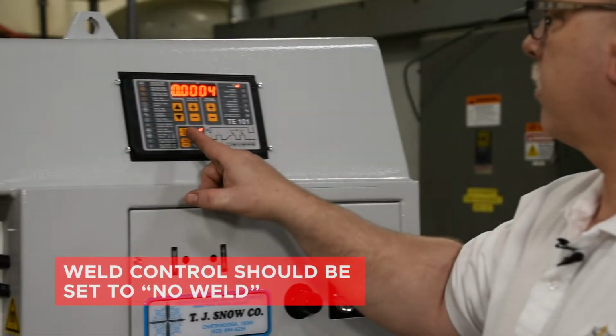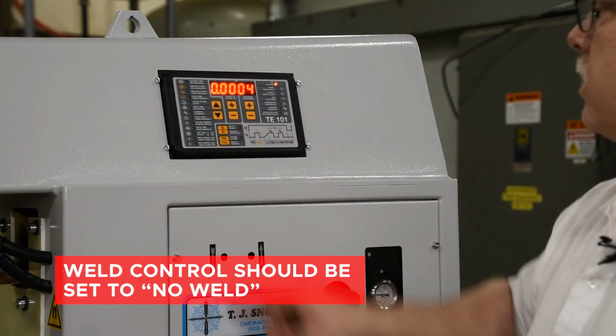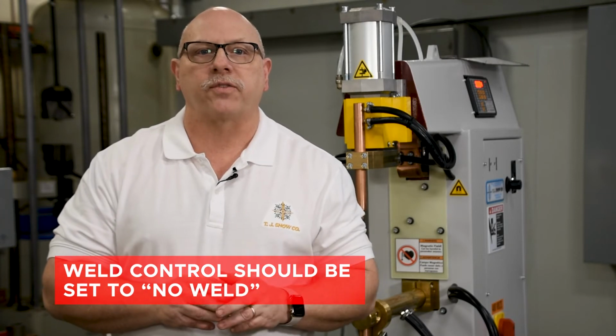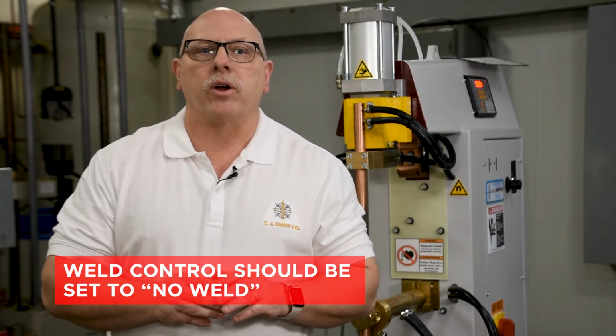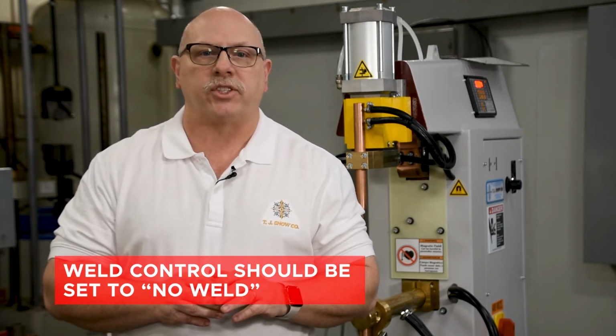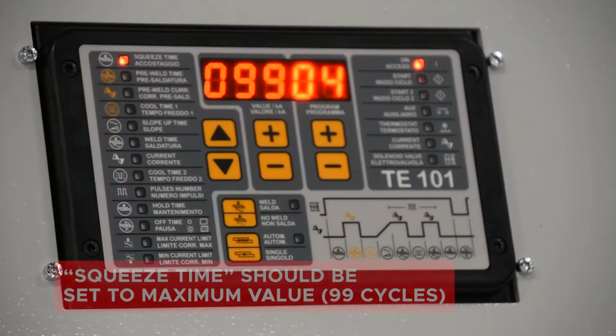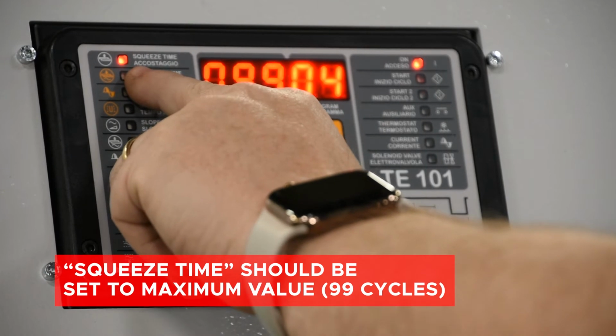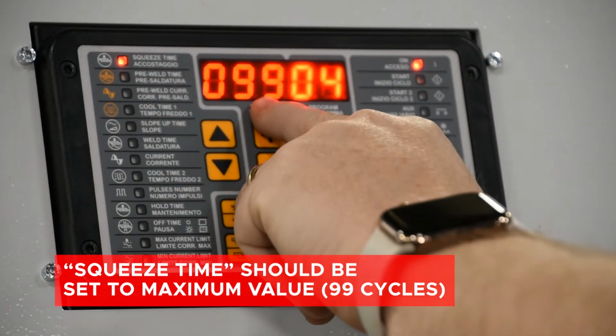With the proper tools in hand, we will begin by setting the weld force. It is required that the weld control is in the no weld condition before performing this function. This is so we don't weld through the force gauge and damage the instrument. Also, we need to ensure that the squeeze function on the weld control is at its maximum value of 99 cycles. In this example, we will be using 18 gauge mild steel with a force requirement of 650 pounds.